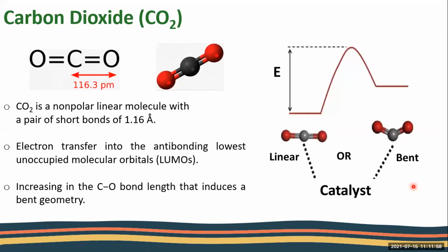So if we look at the carbon dioxide molecule, we can say that carbon dioxide is a non-polar linear molecule with a pair of short bonds of 1.16 angstrom. And if we add a catalyst, there is electron transfer from the metal of the catalyst toward the carbon of carbon dioxide, and then the electrons will move to the LUMO orbitals, and that results in increasing of the CO bond length that induces the bent geometry of CO2 and lets us cleave this molecule and get other products.